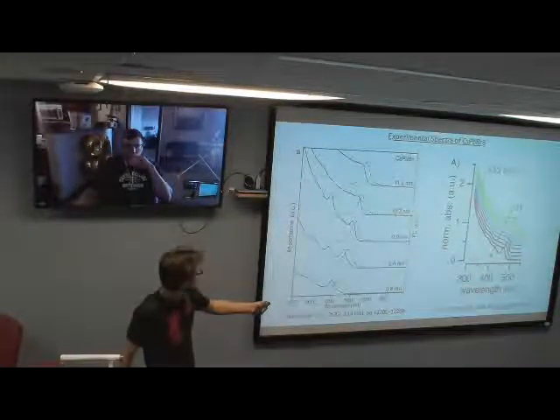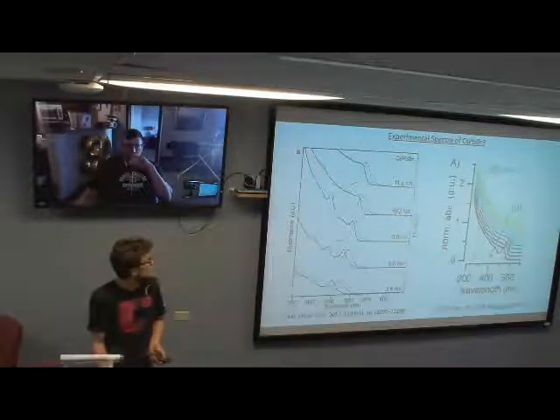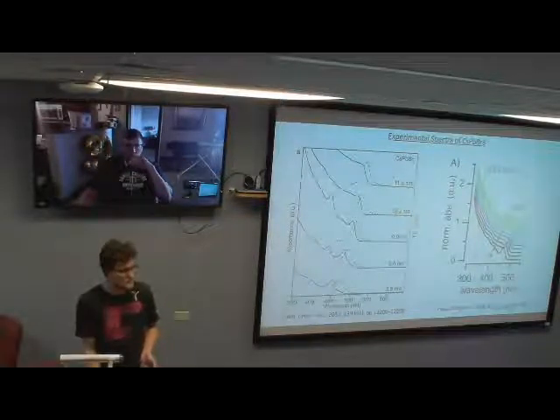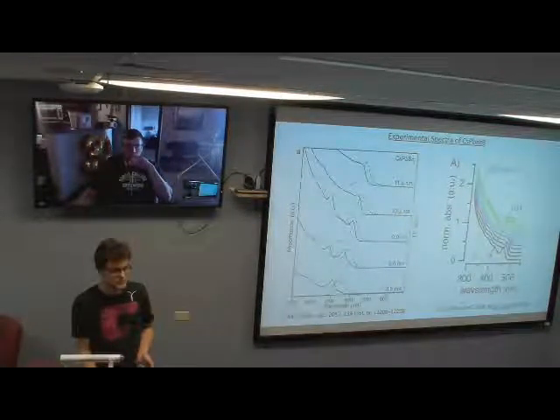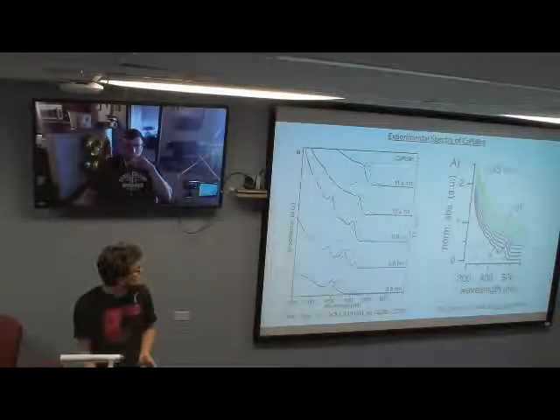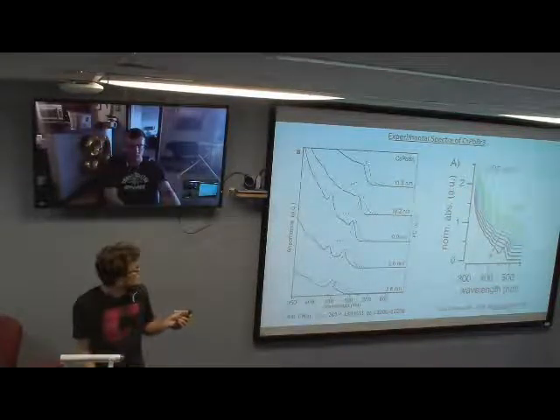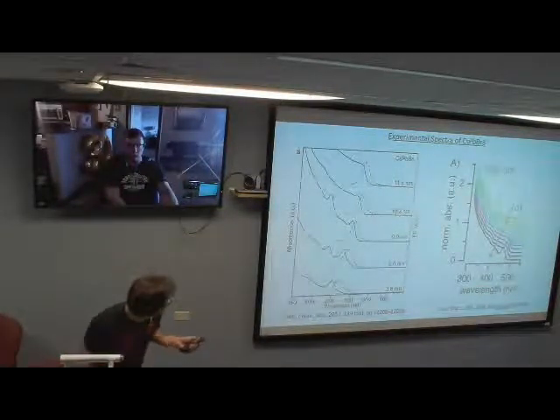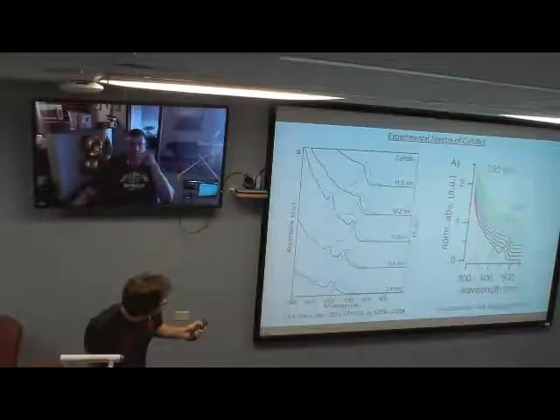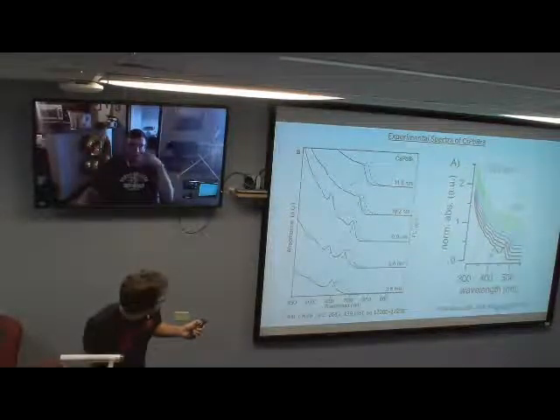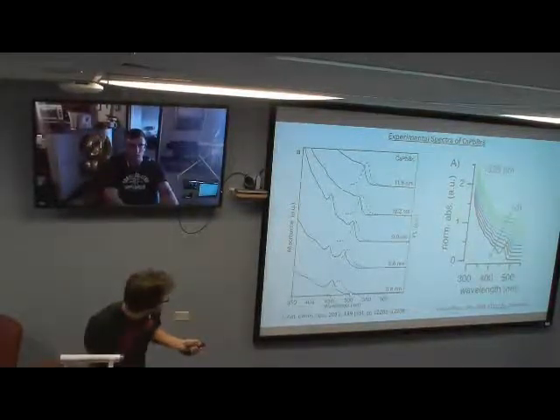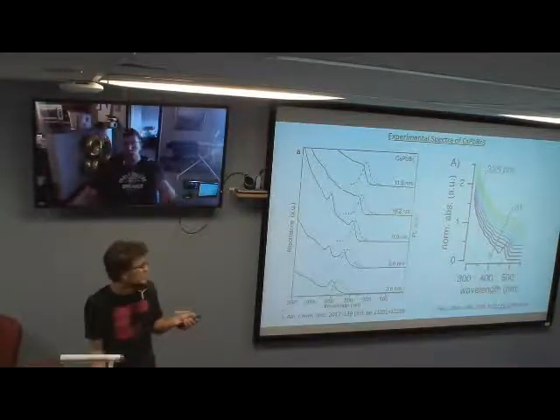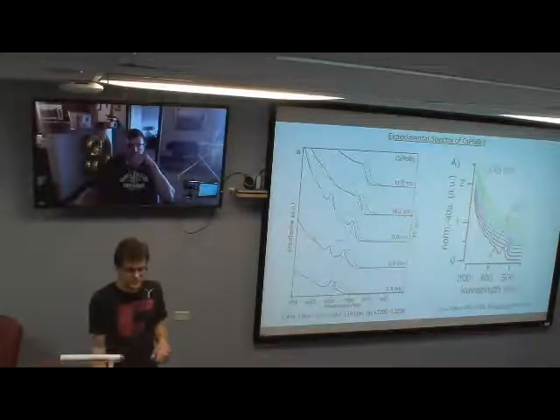So it means if I go to 12, 13 and so on size, then the spectra will not really be shifting and changing after that, right? Right. After 12 nanometers, I expect no really significant changes to the spectra to be noticed, either in energy or in the shape. Yeah, they should all be emitting around 510, 520 for anything above like 10 nanometers.